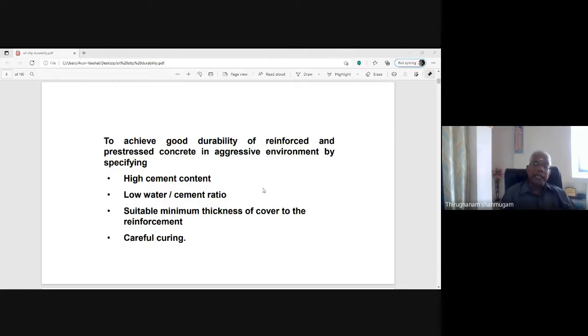So whatever the grade of concrete, you have to maintain your cement content. That is also because of the durability considerations. Because higher cement content induces shrinkage cracks. Shrinkage cracks formed means automatically permeability comes. So durability deteriorates more and more, that is, the concrete is susceptible to deterioration. That is why the cement content limit is mentioned.